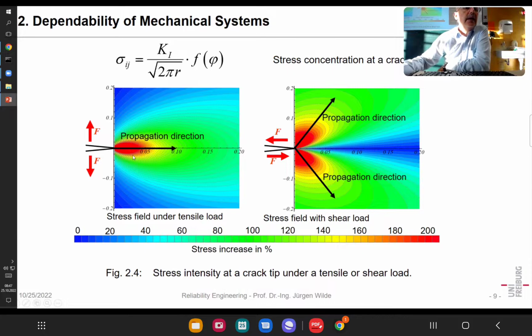Here in the material, we have a stress concentration, and as I mentioned, in tension, we have such an area here where we have maximum distortion, but the stress is proportional to the inverse of the distance from the tip. R here is the distance from the tip, and a second parameter is the stress concentration. That mainly depends on the size, that means how big that crack is in that direction.